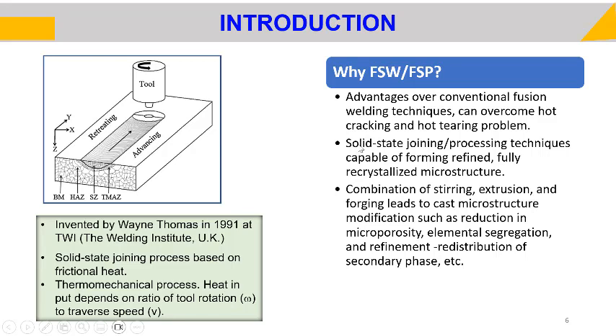It is used as a joining technique because there are certain advantages, especially for aluminum and aluminum alloys which are difficult to join by conventional fusion welding techniques. Fusion welding suffers from issues such as hot cracking, tearing, and change in composition during welding. All those things can be overcome by FSW because this occurs in solid state — there is no liquid involved.